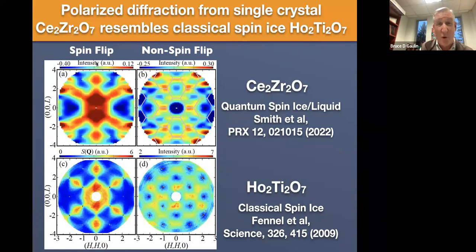So again, only in the spin flip channel, we see this quasi-pinch point in cerium zirconate, but in holmium titanate, in the classical spin ice system, it's clear that there are sharp pinch points both in the 00L directions and in the HHH directions, and we pretty clearly do not see them in the HHH directions in cerium zirconate. Then in the non-spin flip channel, in holmium titanate, they observed what's referred to as zone boundary scattering, so diffuse scattering that follows the FCC Brillouin zone boundaries, which are indicated as these sort of honeycombs in gray in the top right-hand panel here. And we actually see the same thing in cerium zirconate.